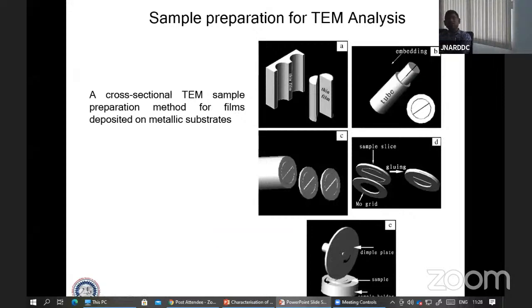And suppose you have a coated material, so how can we see the cross-section or the thin film coating under the transmission electron microscope? As shown in this figure, this is a thin film coated upon the bulk material, and you have to cut like this and make a tube, and then within the tube it has to go inside, so that there are two half-circled blocks. Then we have to slice it with 0.5 mm thickness. By using the dimple grinder, we have to grind the sample, and we need to use the ion beam miller for further thinning. Then the sample will be ready for the transmission electron microscope.